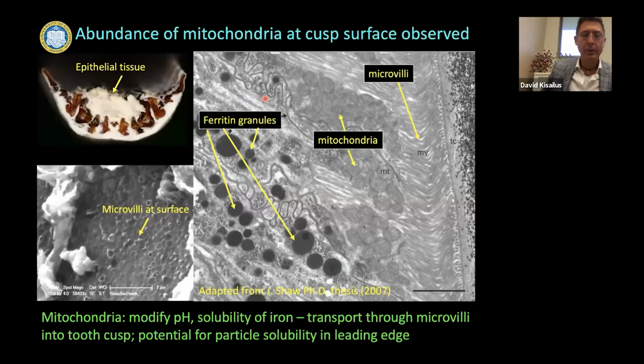And Jeremy Shaw, who did a really wonderful study back in 2007, 2008, showed that these microvilli, so this is where the epithelial tissue would be. The tooth would be here on the right side. You can see some mineral forming. What Jeremy hypothesized was that the iron is being transported into the tooth. It's stored in ferritin-like structures, and ferritin is a ferric iron, Fe3+, that's not very soluble. We also hypothesized that maybe the ferric iron is reduced to a ferrous iron and transported through these microvilli into the teeth where they're subsequently reoxidized to form the ferrihydrite.